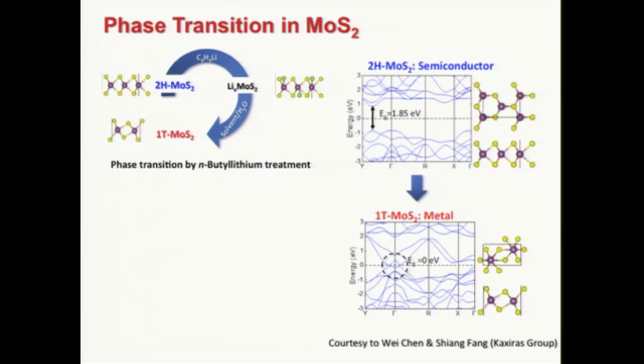Almost all of these transition metal dichalcogenides have a metallic phase beside their semiconducting phase. And it's relatively easy to switch between these two phases. They're reversible. In case of MoS2, we typically use a metal organic compound like n-butyllithium. We just dip the sample in the solution, keep it for a while, and then rinse it. And then you have the metallic one. To go back to the semiconducting one, you just need to heat it up.